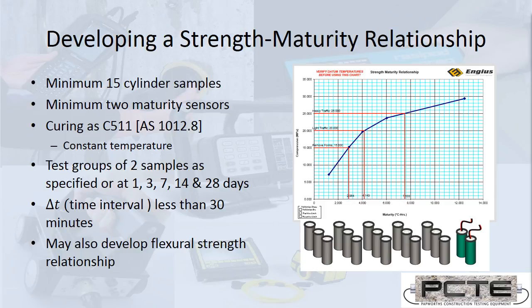Similarly, if it's such a big batch of cylinders that they can't be cast at the lab in one go, the standard does mention that they should be cast batch 1, batch 2, and then one from each batch broken during the appropriate breaking times, the 1 day, 3 days, etc., or as required. The other key criteria of that standard is that the time interval where the temperature is logged is every 30 minutes at most. It could be less, it cannot be more.